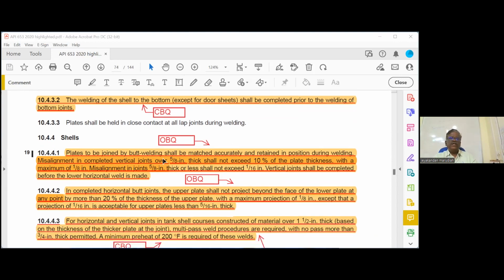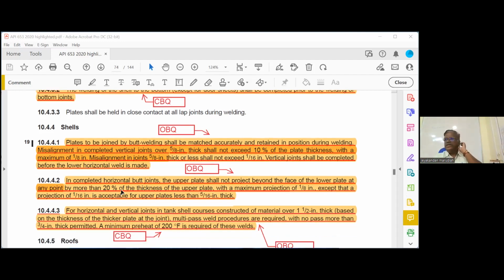Plates should be joined, but butt welding shall be matched accurately in the position 5 by 8 inch. For 5 by 8 inch, the mismatch shall not exceed 10% with a maximum of 1/8 inch. Okay, this is the same 650 requirement. 10.4.4.2 horizontal joint, again there is the same 650 requirement.